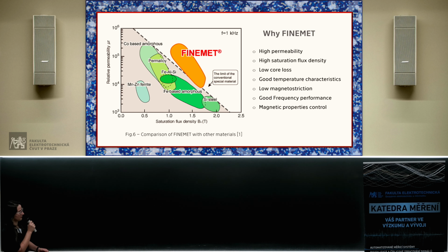Before, we already did some experiments with permalloy, with amorphous wire, and with Co-based amorphous alloy. These materials are conventional, and they give good results, but we could improve the work of the sensor by trying another type of material, which is Finemet. It's nanocrystalline. And why is it good? Because it combines properties of two types of materials: crystalline, like permalloy, and amorphous alloy.